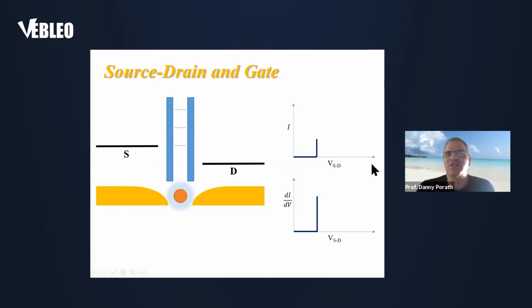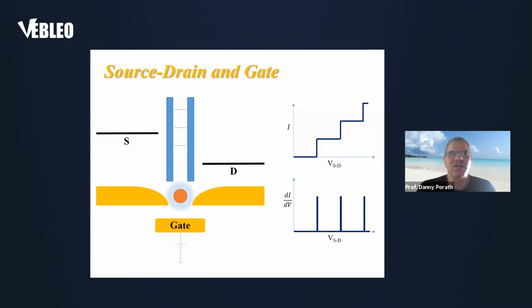In the current-voltage scheme, there will be no current until we hit this energy level, and then there is a rise of the current versus the voltage. Then we raise the voltage again until we hit the next energy level, and then we have again another rise of the current, and so on and so forth. And if we look at the derivative of the current versus the voltage, we will have these peaks that will tell us the positions of those energy levels. This is the measurement when we have just two electrodes.